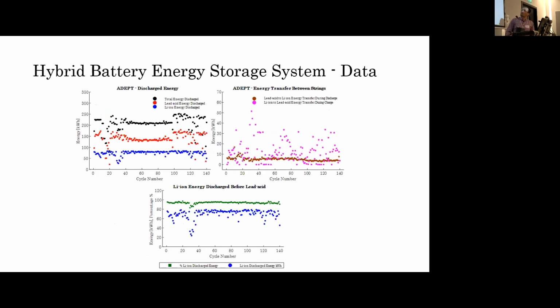So we have some values in here. What you can see on that graph is the total discharge energy for each cycle. The system is around 270 kilowatt hours. We didn't discharge it completely, so we kept it around 210, 200. The black dots are the discharge energy. You can see that in the last few months it was run at a lower power. That means we had some extra energy, because lead acid likes to be discharged at a low rate, so we have more energy from that. That's why we see an increase over there. On the contrary, lithium ion was quite constant, right? Lithium ion doesn't care about the discharge rate.